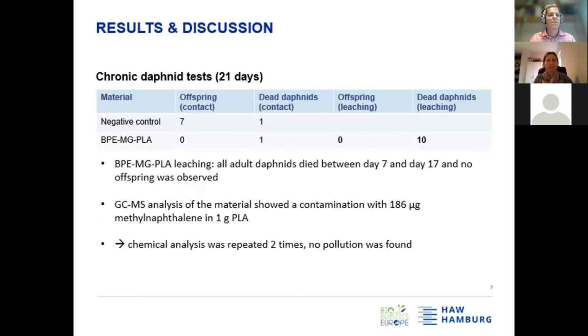So now I would like to explain a little bit more about the BPE-MG-PLA material. And as you can see, in leaching tests, in chronic leaching tests, we didn't have any offspring, and also all adult daphnids died between day 7 and day 17. So this was a really strong reaction of the daphnids towards the material. And we analyzed the media by GCMS.